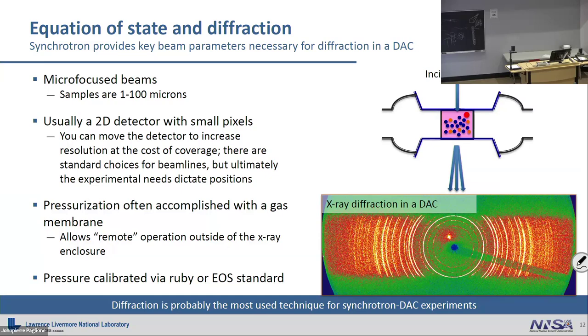So in this case, because you're going through the diamond, your choice of gasket is really not terribly critical in terms of the experiment. It's just to make pressure. So if I were doing this, I would almost always use a rhenium gasket here because it's a very strong metal, and we know that it's going to allow us to have a stable hole that goes up to high pressure. And then a lot of times what we do at Livermore is we almost exclusively gas load ourselves